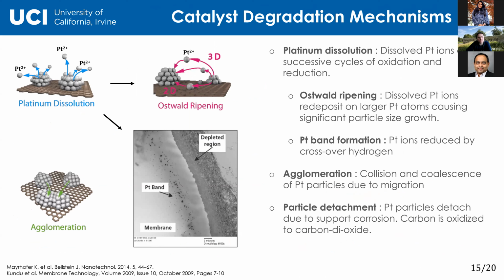As you operate a fuel cell, you cycle it in a potential range where platinum oxidizes and redeposits. So you have continuous platinum dissolution, and then it redeposits from smaller particles onto large particles, which is called Ostwald ripening. This is a thermodynamic phenomenon where larger particles have smaller surface energy. So essentially platinum wants to deposit onto those. Then you can lose platinum area through agglomeration.